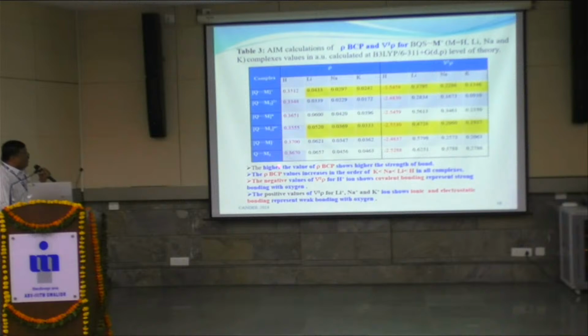Here, all the values of rho BCP show the strength of the bond. If we see the trend, potassium to sodium, sodium to lithium, lithium to hydrogen, these values keep increasing and the strength of the bond increases. Rho BCP values increase in the order of potassium to sodium, lithium to hydrogen, and these negative values of del square rho with hydrogen cation show a covalent bond.